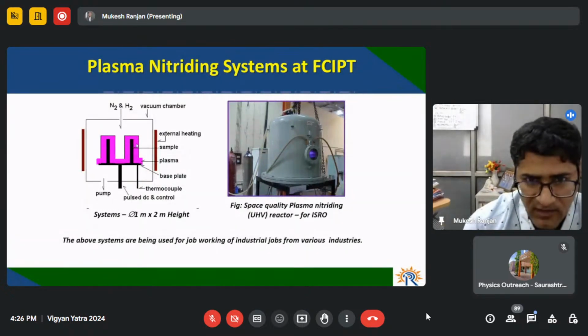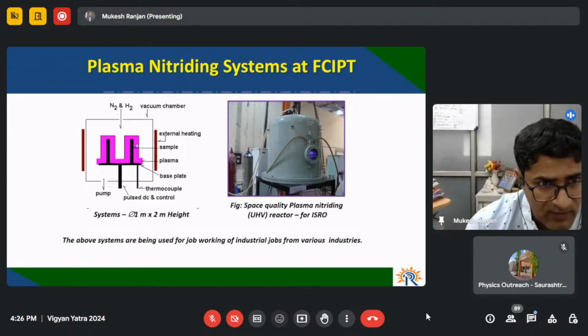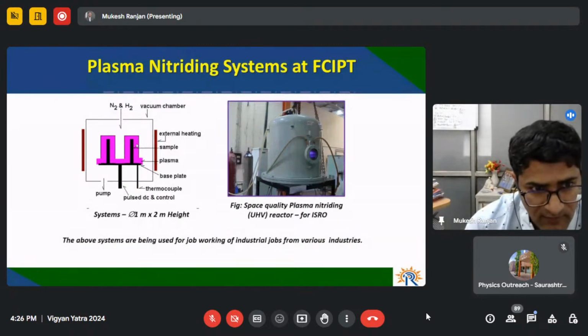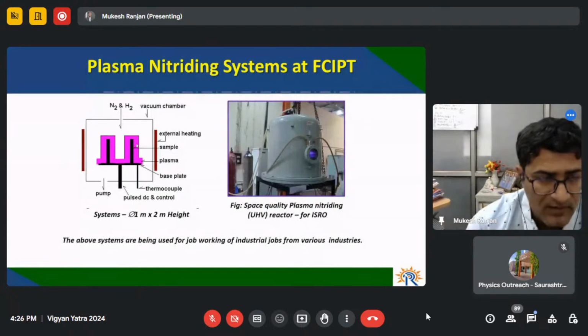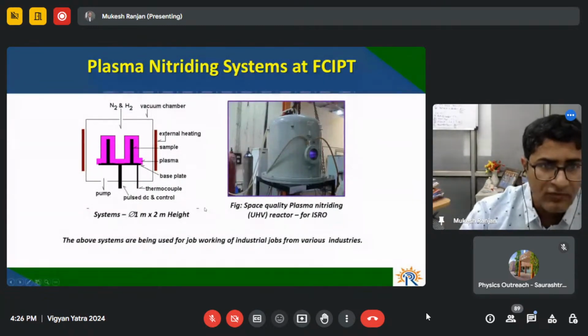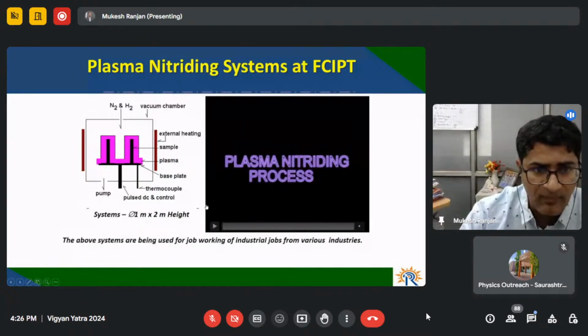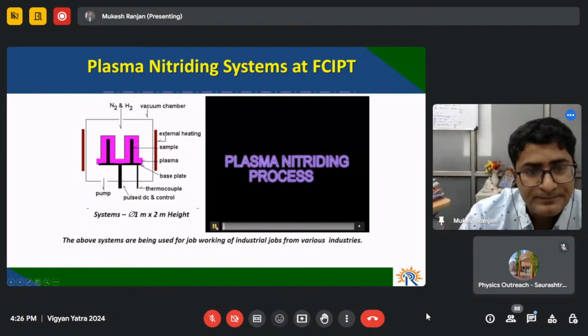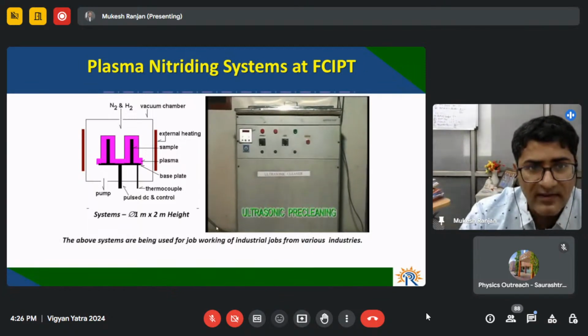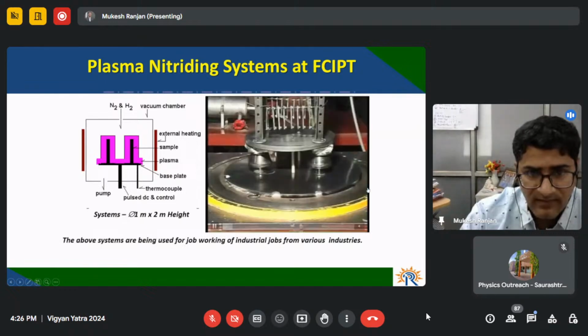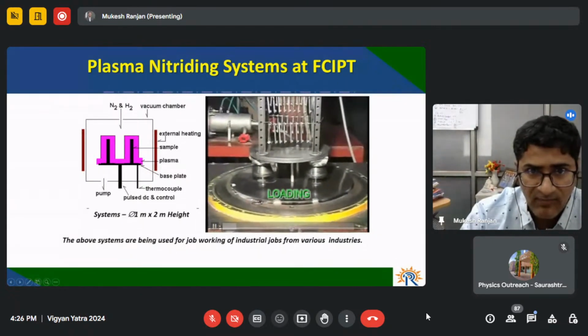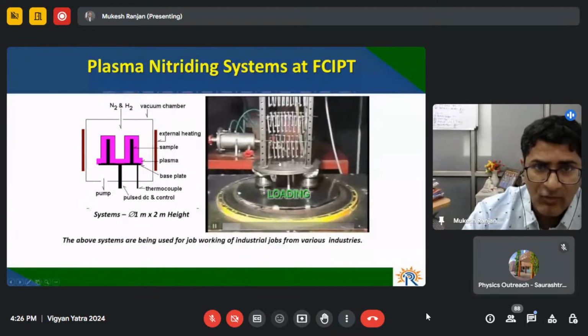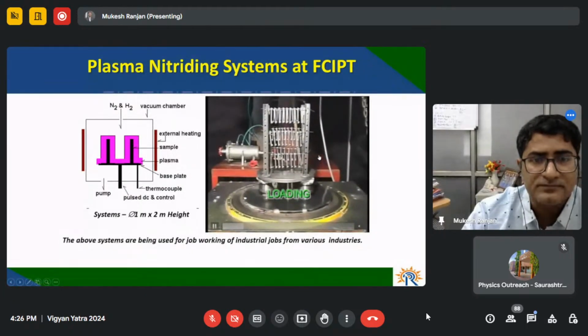The nitrogen ions diffuse inside the steel up to hundreds of microns, depending on the dose you are giving, and they make it anti-corrosion resistant and also increase the hardness of the steel component. I'm going to show you a movie again of how the plasma nitriding process is done. You can enjoy this movie. You can see in this system that first we clean the samples and then mount them in a chamber. These are some tools which are hanging and going to start the plasma nitriding process.